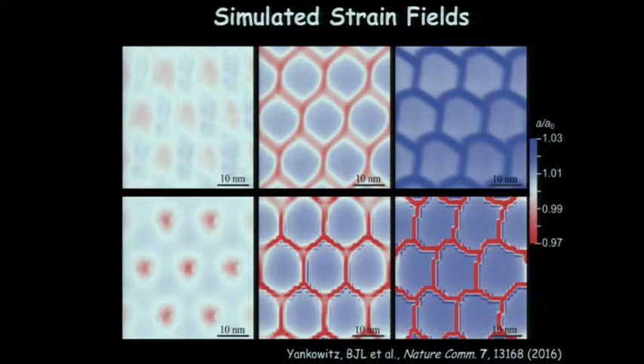And so you can see that when the tip, this was the condition of the tip being far away, there's a slight variation, and that's just coming from the natural matching between them. Here's when you're pressing down hard, we get pretty good agreement between them. When you're pressing down very hard, as I said, this is being hysteretic, and the calculations expect to have a very large contraction along the domain walls. We don't see that, and I'm not sure if you should really take too much away from the fact that we don't see the same there.